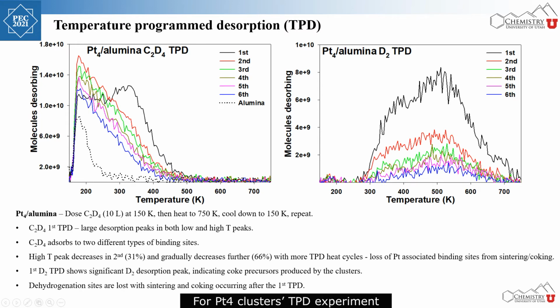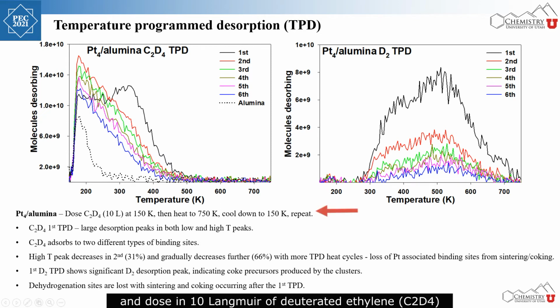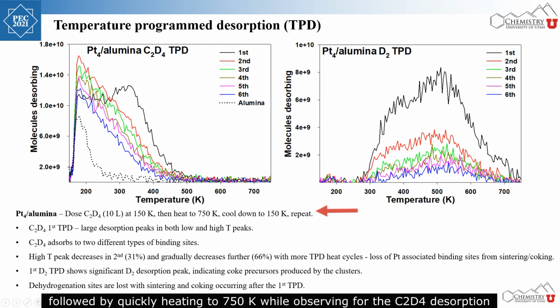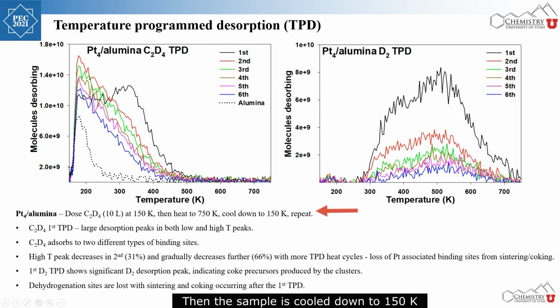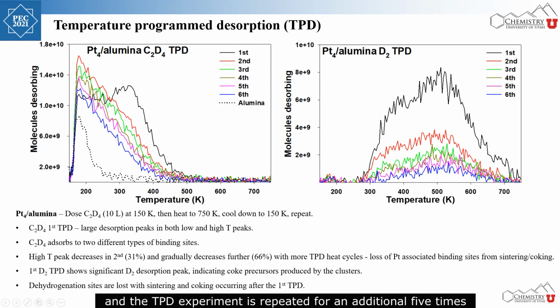For platinum-4 clusters TPD experiments, we place a platinum-4 alumina sample in front of a mass spec and dose 10 Langmuir of deuterated ethylene, C2D4, followed by quickly heating to 750 Kelvin while observing for the C2D4 desorption and the D2 desorption from dehydrogenation via the mass spectrometer. Then the sample is cooled down to 150 Kelvin and the TPD experiment is repeated an additional 5 times, so a total of 6 TPDs are performed.